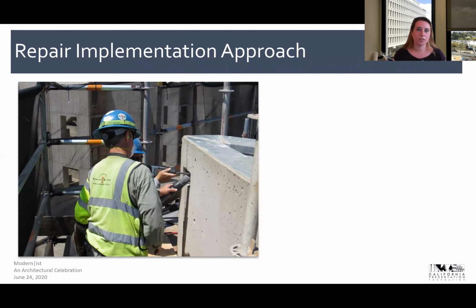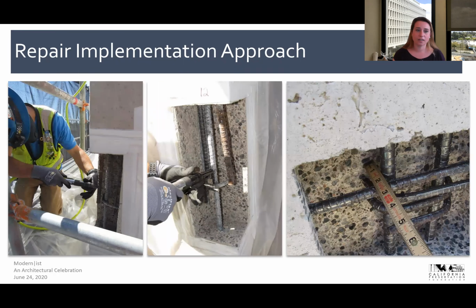So then we went through a trial repair phase and worked with the contractor to start implementing these repair approaches. And again, we needed to make sure that we had removal techniques and surface prep techniques to achieve a well-bonded, durable, sound repair that's going to be bonded to the substrate. In order to achieve that, we were looking at very careful removal without damaging adjacent material, right? So small chipping hammers, but also utilizing a needle scaler to clean corrosion product off of the bars and get them prepared to receive concrete, as well as prepping the lightweight aggregate surface to receive the repair material to make sure that they were bonded.